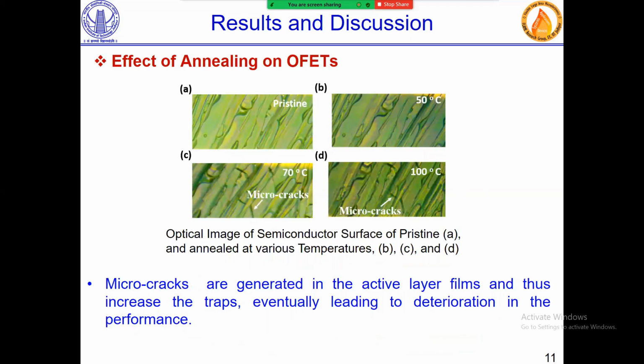This study is also supported by optical images of the semiconductor surface of pristine and annealed samples at various temperatures. Here, micro cracks are generated in the active layer at the temperatures of 70 degrees Celsius and 100 degrees Celsius. Thus, these generated micro cracks in the active layer film increase the traps, which eventually leads to deterioration in the performance.